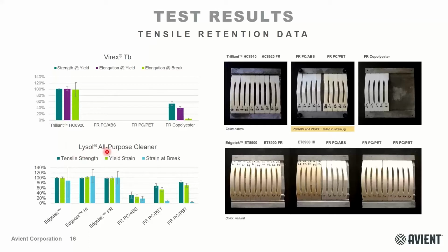We did a similar thing for our consumer product line, the EdgeTech 8900 series, where we looked at Lysol all-purpose. We've also tested a number of other disinfectants, which I'll show on the upcoming slides. But again, here, what you can see is that there's really no visual signs of stress cracking. PCPBT actually also held up pretty well against Lysol in this test in terms of visual observation. But with the FR PCABS, you can see maybe some cracking here, but definite signs of crazing. And the same on the PCPET. Again, you can see obvious signs of crazing in that part.